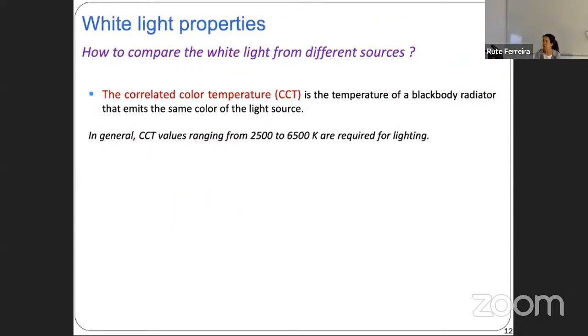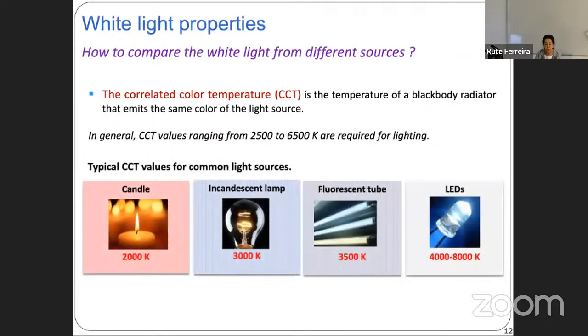To understand better the challenge in the field, we need to understand how to compare the white light from different sources. There are two main figures of merit. One is the correlated color temperature, CCT, which is the temperature of a black body radiator that emits the same color as the light source. In general, CCT values range from 2,500 to 6,500 Kelvin. For instance, a candle has a CCT of 2,000 Kelvin and an incandescent lamp 3,000 Kelvin, a little bit higher for a fluorescent tube, and for LEDs, CCT typically varies between 4,000 and 8,000 Kelvin.